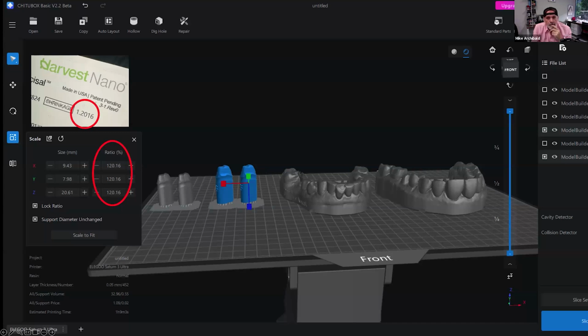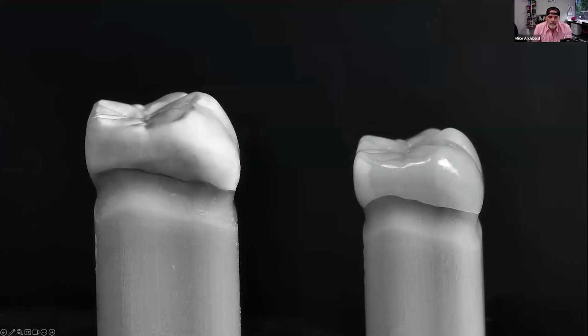So yeah, Mike, what we have here is a build plate where you've got an upper and lower model and a couple dies, and then you just duplicated the die, and you enlarged it by 120.16%, which is tied to the shrinkage rate of the zirconia at 1.2016. So by enlarging those dies by the same shrinkage rate as the zirconia, you're then going to have an enlarged die that perfectly fits your green state zirconia.